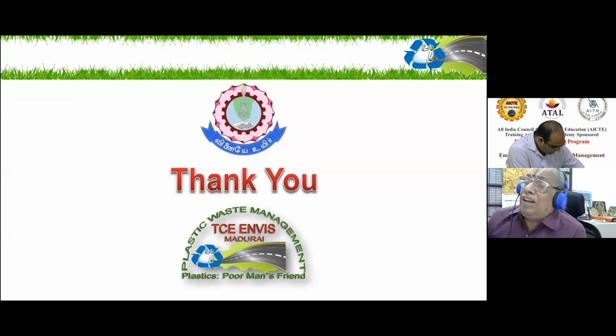Yes, all films. I missed the word film in my lecture. You can use films of a thickness of 90 microns. Films, carry bags, chocolate covers, kurkure covers, all those films with a thickness of 90 microns can be directly used, cut into small pieces for the road. If the thickness increases, we have to modify certain criteria. But generally, what we need is to collect the waste, dry it, cut it, and give it. Not even cleaning is necessary.